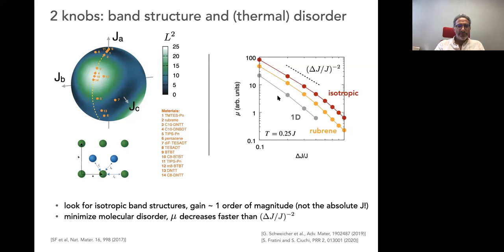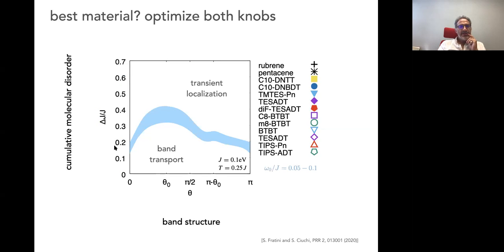So these two pieces of information, the two knobs, can be condensed together in one graph. That is here. Here I have this band structure parameter theta that controls how isotropic it is. So 1D would be here, isotropic would be here, and on the left axis it's disorder. So first thing, of course, if disorder is low, you have band transport. If disorder is high, you have transient localization. Second thing, for a given disorder, this is what you're seeing here. It's easier to get band transport if you're on an isotropic material than on a 1D. So this is just a summary of what was written there.